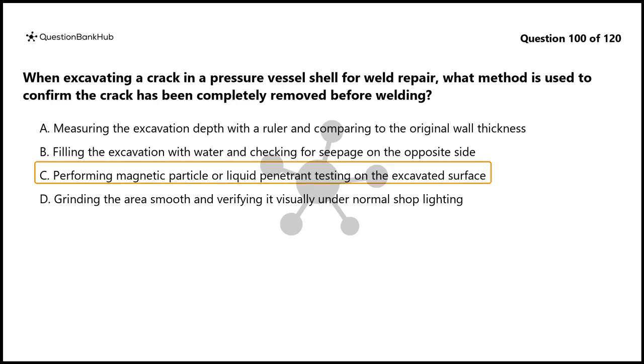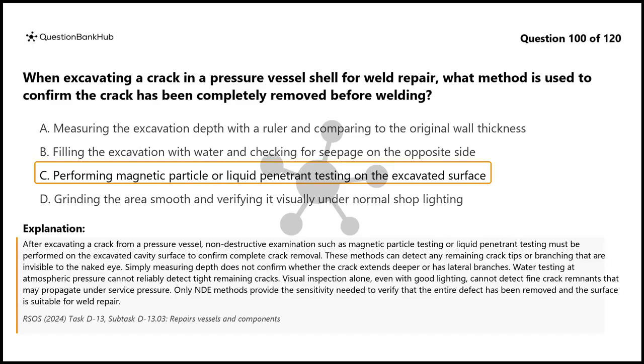The correct answer is C. After excavating a crack from a pressure vessel, non-destructive examination such as magnetic particle testing or liquid penetrant testing must be performed on the excavated cavity surface to confirm complete crack removal. These methods can detect any remaining crack tips or branching that are invisible to the naked eye. Simply measuring depth does not confirm whether the crack extends deeper or has lateral branches.